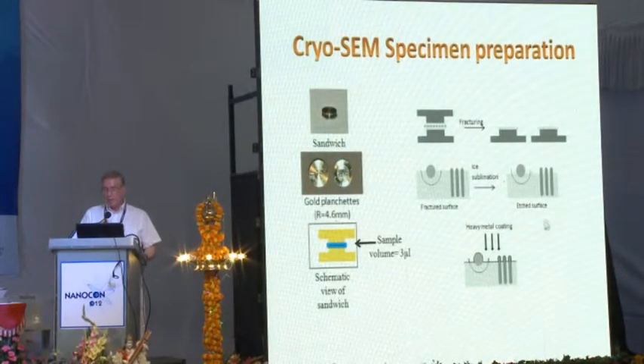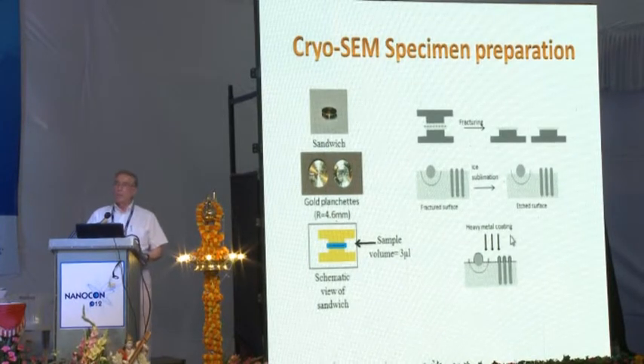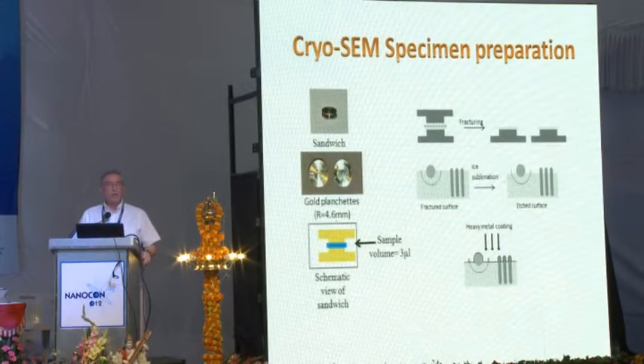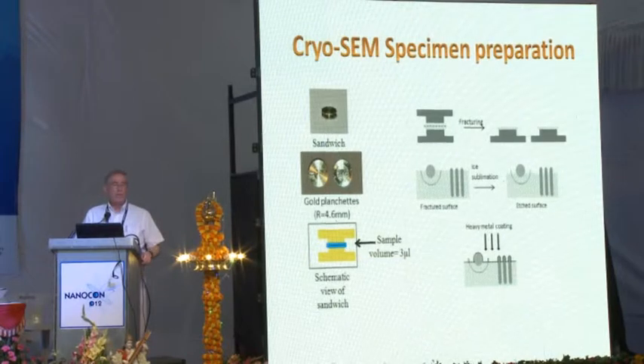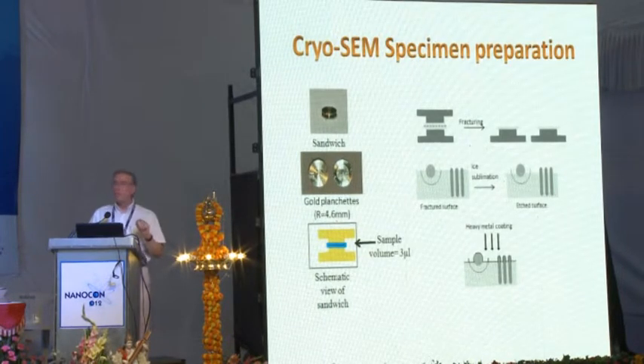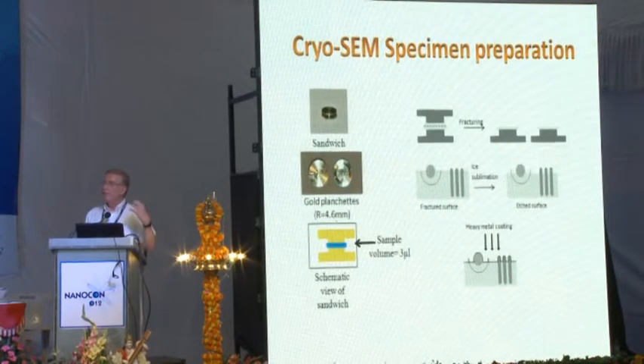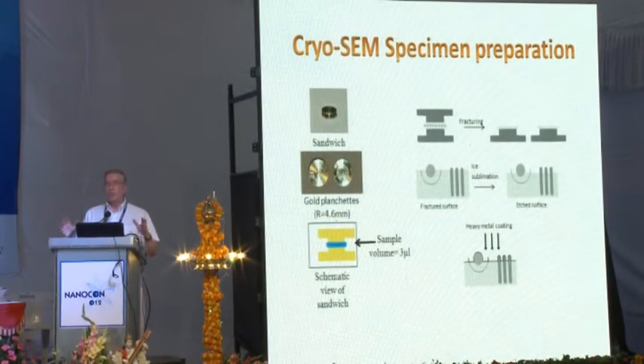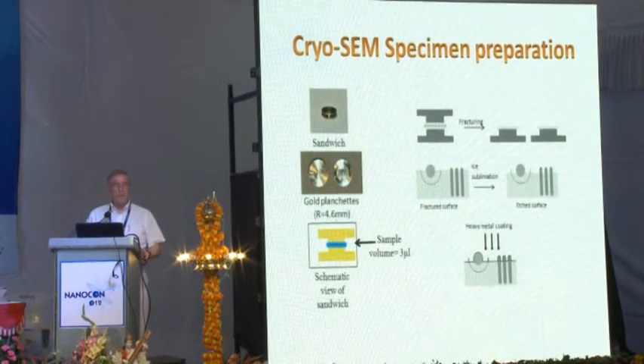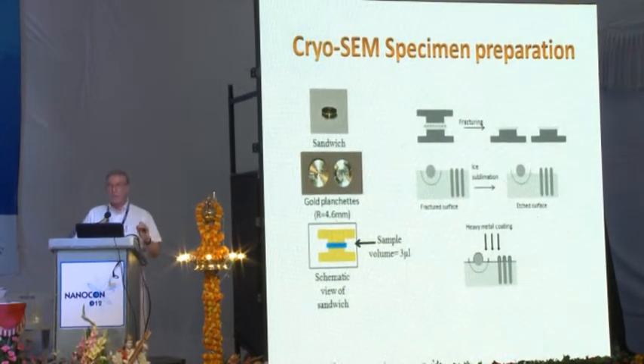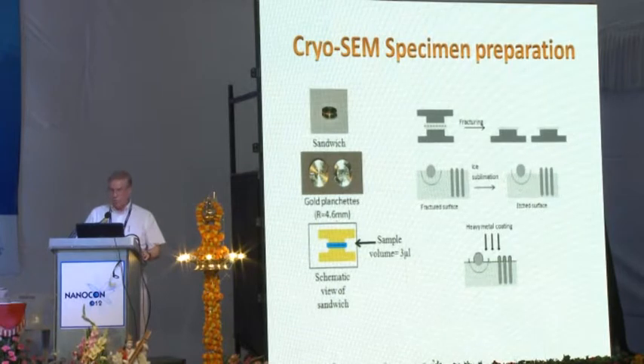And if you want, you can also coat with a thin metal coat in order to make the specimen conductive. This is actually not needed if you use the right low voltage, because if you use the right low voltage, the number of electrons hitting will be equal to the number of electrons emitted, and then you don't need conduction in order not to charge your specimen. So you have to really select your parameters very carefully.